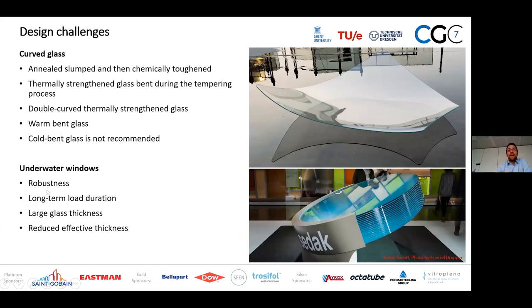Curved glass is quite a challenge, also in super yachts, particularly when it's combined with coatings, because there are several limitations there. So all the methods that are already well known in architectural industry can be adapted. Of course, cold bend glass is not recommended due to the high bending stresses already induced there. And together with the 40 MPa limit, this is not an option. Underwater windows is the latest trend. Their design is focusing mainly on robustness.